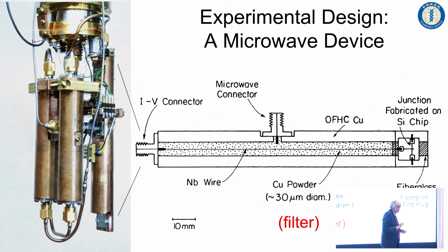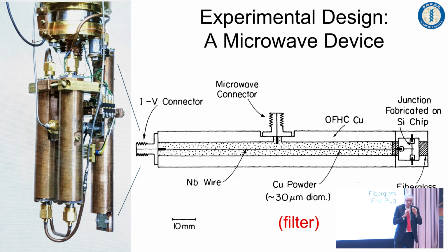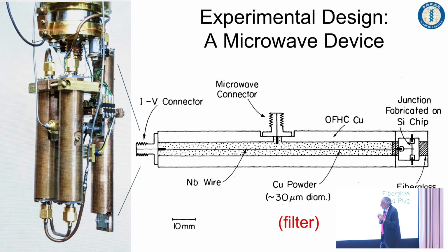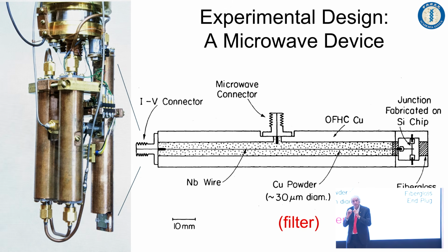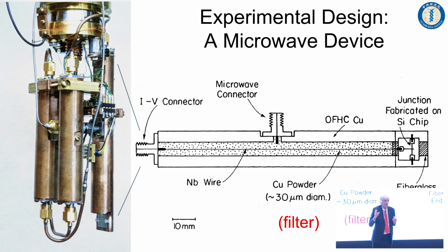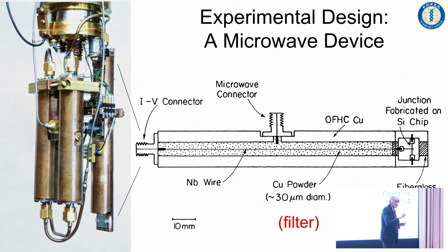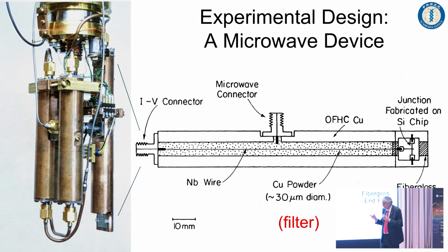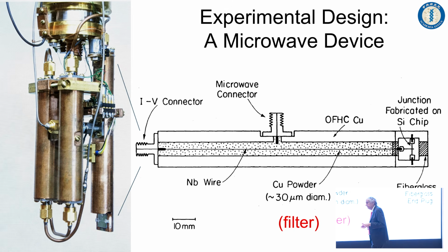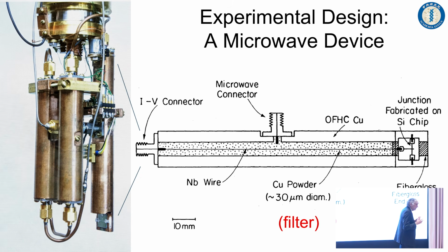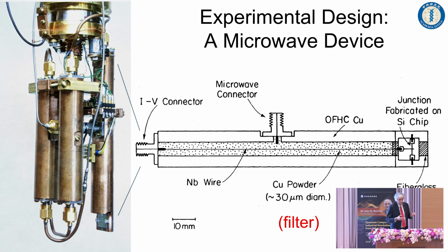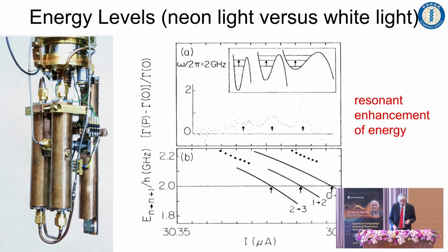And what we're going to do in the experiment is we put the current just below the critical current, and then every once in a while it'll fluctuate from the 0 voltage state to the voltage state, either by thermal noise at high temperatures or quantum mechanics, quantum tunneling, some kind of quantum phenomenon. It can go to the voltage state a little bit before it's supposed to, ideally. And that's the physics we're looking at. This is the physics of an escape rate, escape system. The escape from the 0 voltage state to the voltage state.